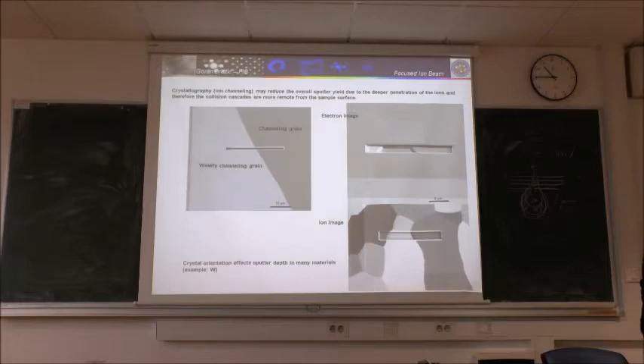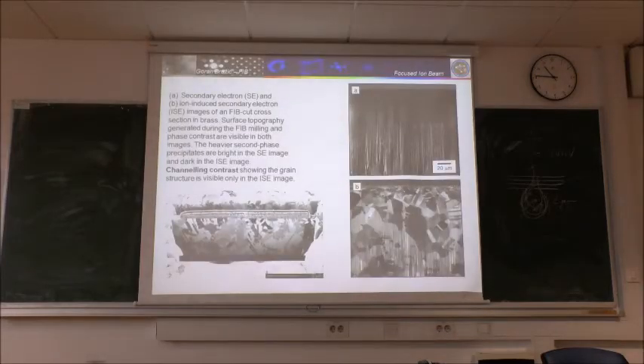for some application? Yeah. This is so-called channeling contrast. If you have channeling, the signal is dark because there are not many electrons and ions, and here is no channeling. And in that case, you can see every grain, it has its own brightness, its own contrast. This means that this one has no channeling, and this one has very high channeling. And you can even see that the depth of the penetration, the efficiency, is different due to this channeling. You might get very nice images using this channeling. And here's some example.